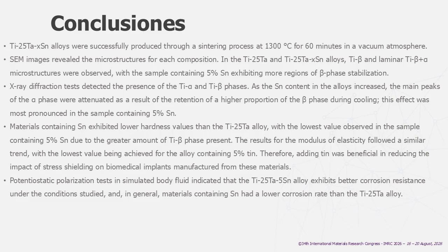Materials containing tin exhibit lower hardness values than the titanium 25 tantalum alloy, with the lowest value observed in the sample containing 5% tin. Due to the greater amount of titanium beta phase present, the results for the modulus of elasticity followed a similar trend, with the lowest value achieved for the alloy containing 5% tin. Therefore, adding tin was beneficial in reducing the impact of stress shielding on biomedical implants manufactured from these materials.